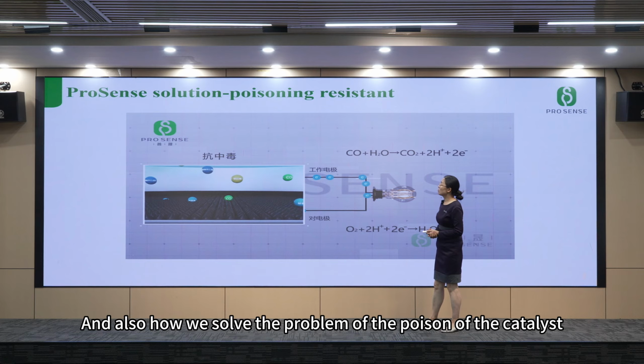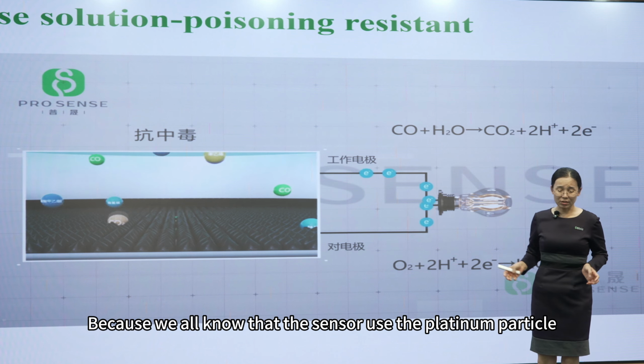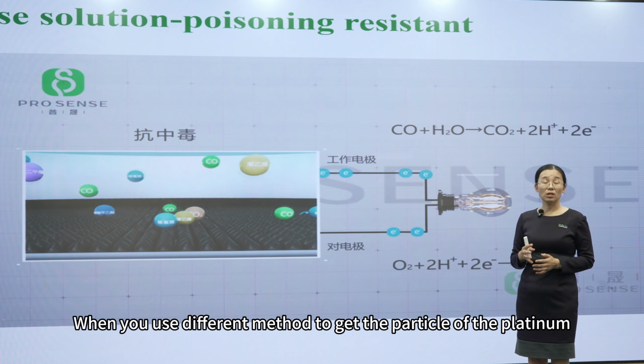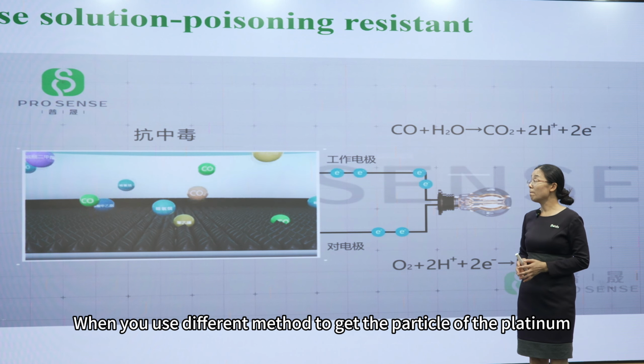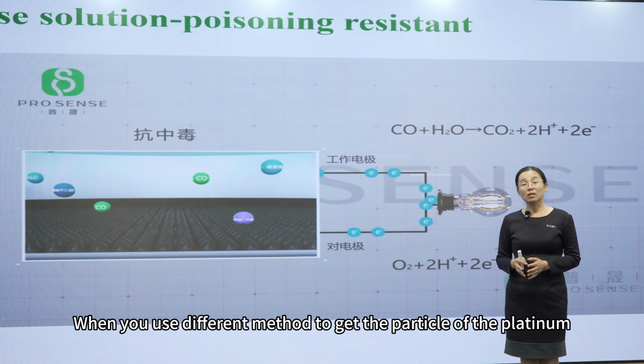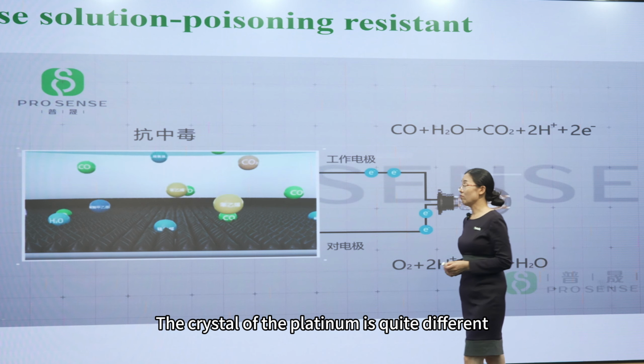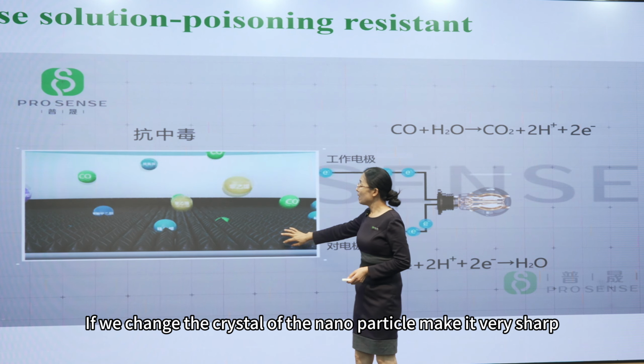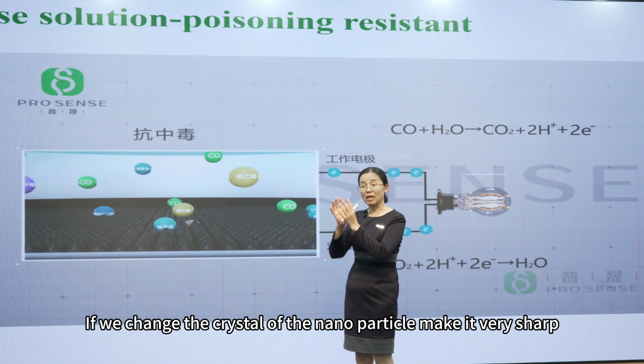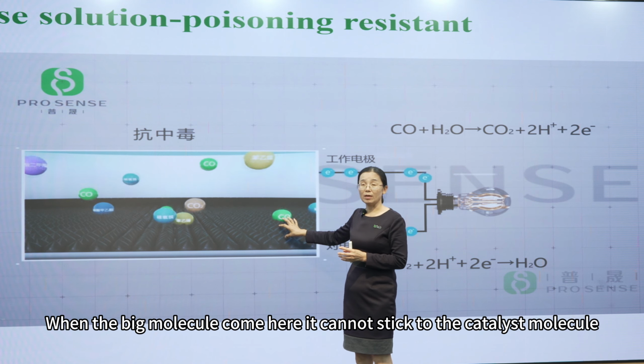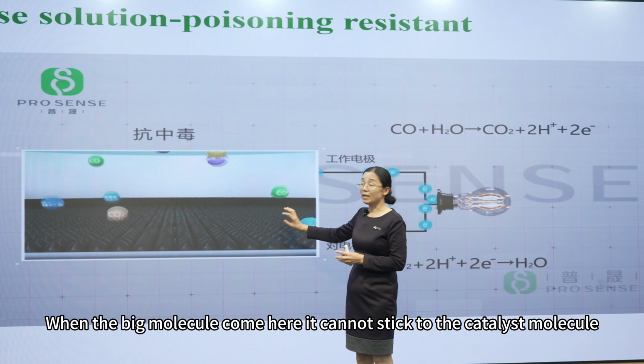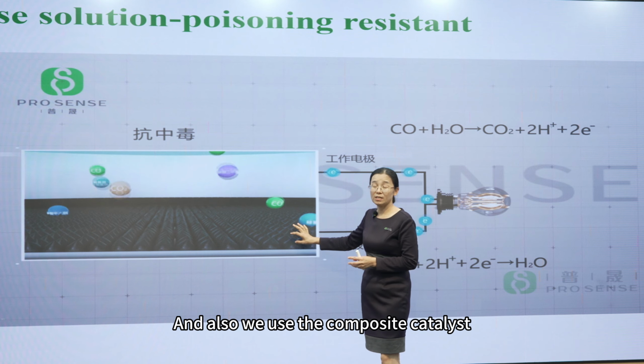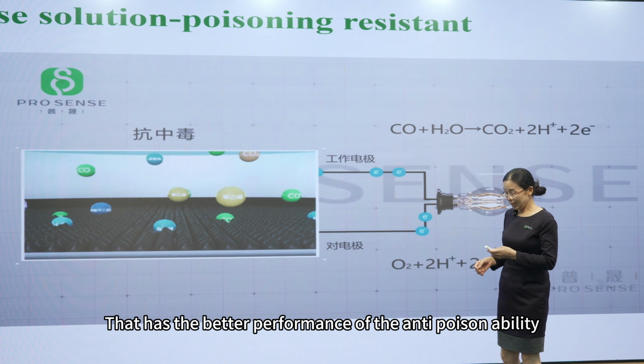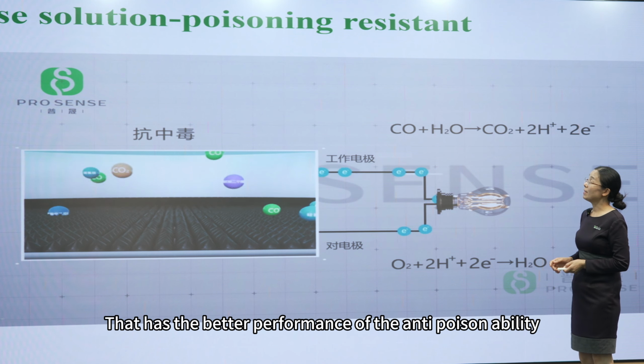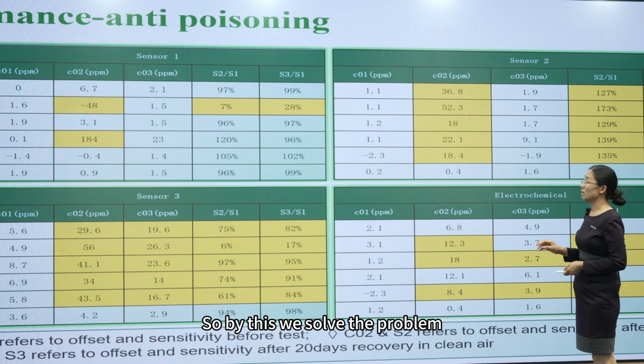And also how we solve the problem of the poison of the catalyst. Because we all know that the sensor uses platinum particles. When you use different methods to get the platinum particles, the crystal of the platinum is quite different. If we change the crystal of the nanoparticle and make it very sharp, when the big molecule comes here, it cannot stick to the catalyst molecule. We can solve the problem. And also we use a composite catalyst that has better anti-poison ability. So by this, we solve the problem.